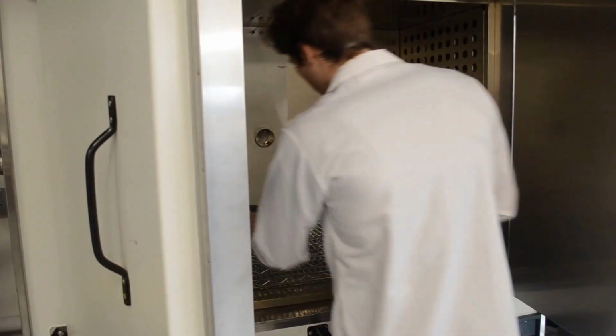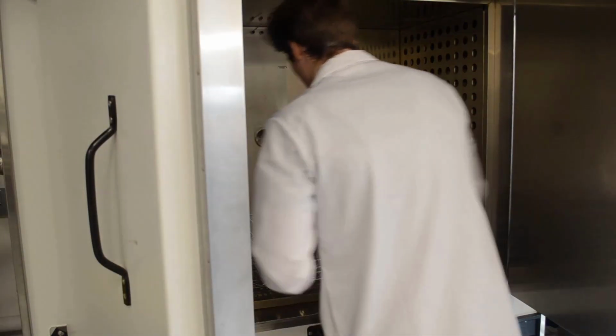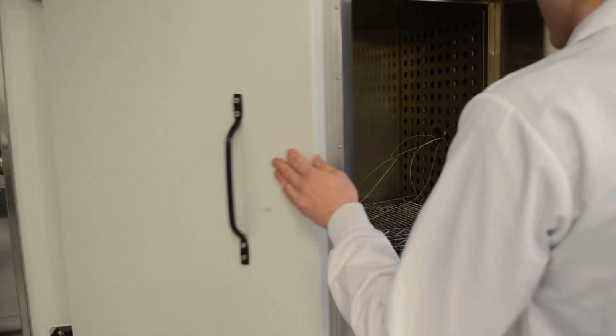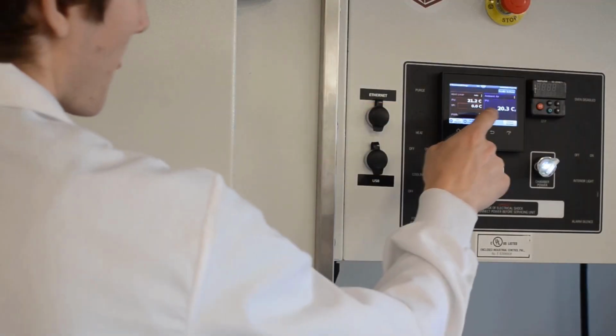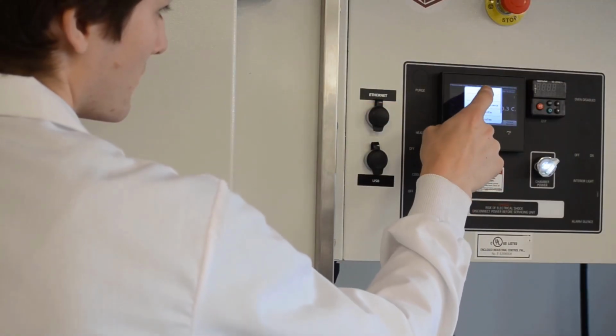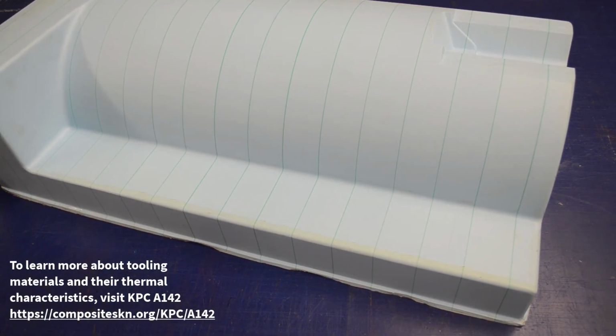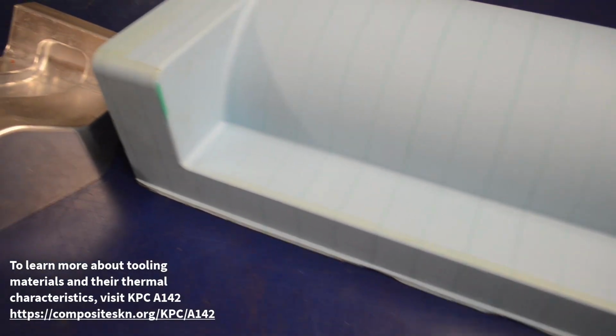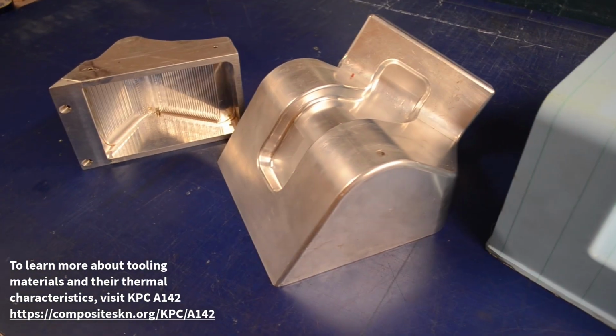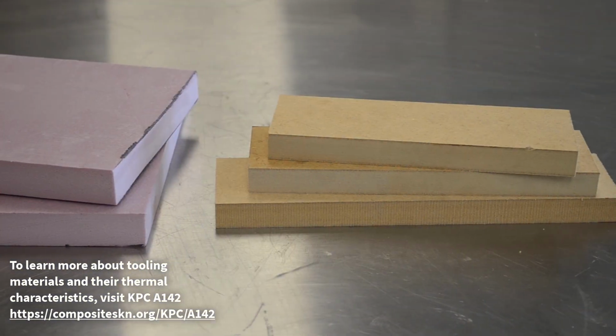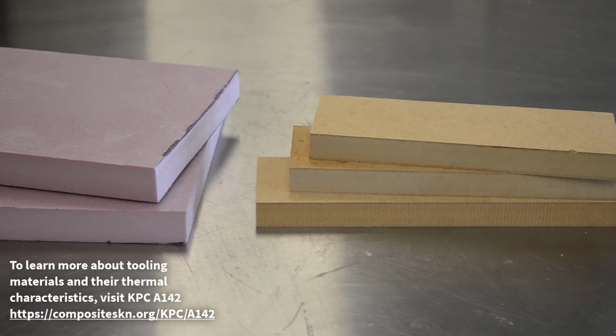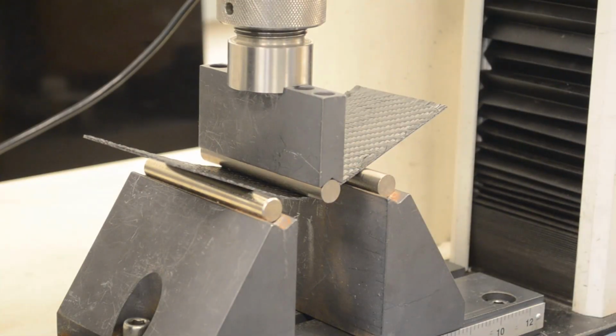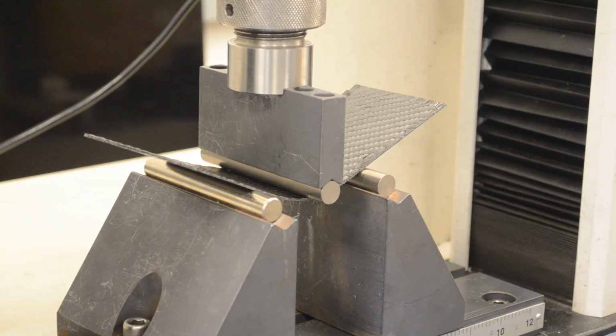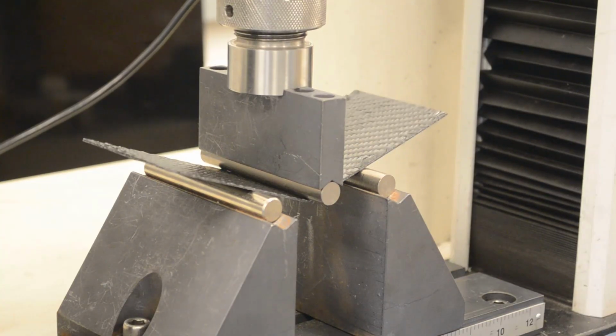Curing can occur at room temperature, but temperature may be controlled at different stages of the process to achieve different outcomes. The wet layup process requires minimal investment in tooling and equipment. Thermal properties are typically less critical for wet layup tools compared to oven or autoclave tools, which allows for a wider variety of materials to be used in their construction, leading to more economical part production. Wet layup typically produces parts with a relatively low fiber volume fraction and reduced uniformity and consistency between parts.